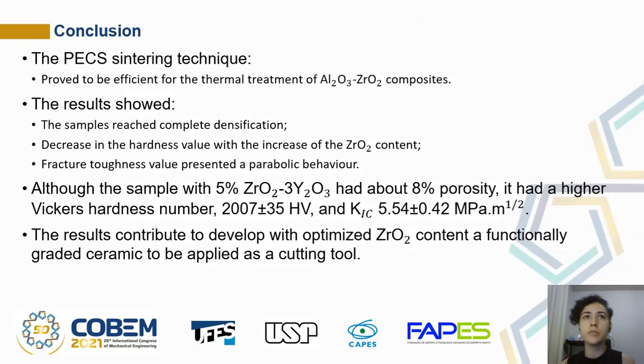The conclusion of this work is that the PECS technique proved to be efficient for the thermal treatment of alumina zirconia composite, and the samples reached complete densification. There was a decrease in the hardness value with the increase of the zirconia content, and the fracture toughness value presents a parabolic behavior. Although the sample with 5% of zirconia had about 8% of porosity, it had the highest hardness and fracture toughness. The results contribute to develop a functionally graded ceramic to be applied as a cutting tool with optimized zirconia content.